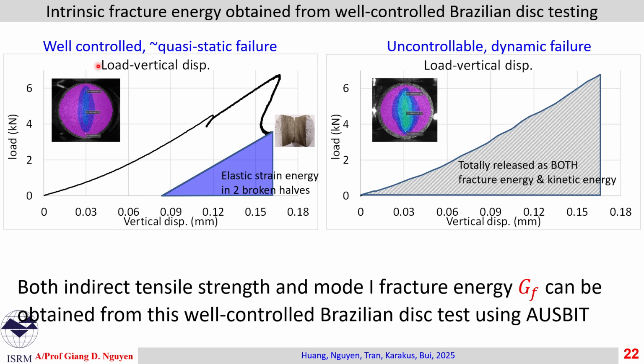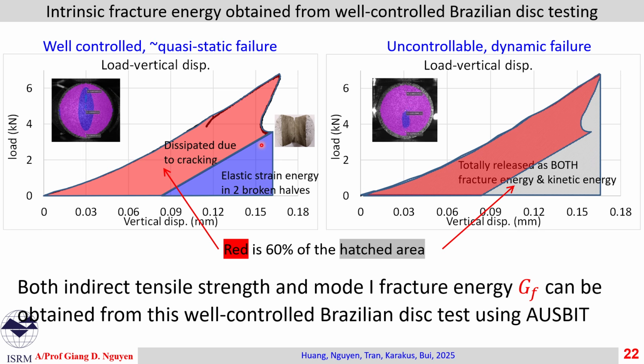So if we do the well-controlled one using AUSBIT, we end up with close to quasi-static conditions, and we can pinpoint the moment of complete fracture and work out the dissipated energy and of course the fracture energy of the material. As you can see here, if kinetic energy or dynamic effects are removed, we get something that is the area here, the red area. This is only roughly 60% of the hashed area. That means the hashed area is the area we got under the uncontrollable configuration.